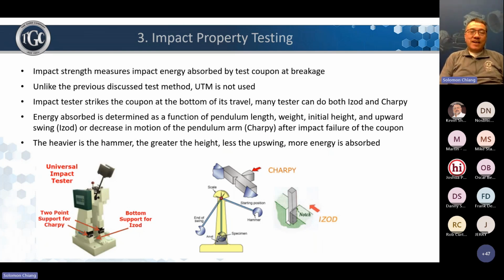Impact. Most IEC or NEMA material standards show impact properties, and in most cases, those are not a very high bar. I have not seen thermoset composite having trouble passing impact property, but it's there, and it's good for comparing material A to material B as far as whether one is higher than the other. It's not very useful for design work, but it's a good comparison between materials, and they are not done by the universal test machine. They have special tests, essentially you swing a pendulum against a coupon and see how much energy the coupon can absorb before it breaks.